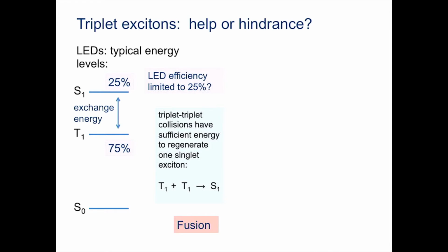And it's already a big deal for organic LEDs because as we bring electrons and holes together in an LED, 3 out of 4 collisions produce a triplet and only one produces a singlet. And that might have limited efficiencies to 25%, but I've already told you that efficiencies are at around 100% for OLEDs. And there have been some very clever ways around energizing the triplets so that they can become directly emissive. One of them is to allow triplets to collide with one another and they can fuse to form a singlet. There's enough energy to do that.